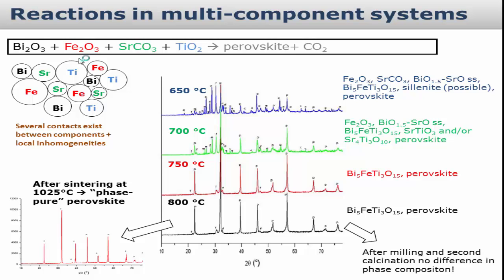This is an X-ray pattern of the mixture of these 4 at different temperatures. You can see that there are several phases that are formed. These patterns are very complex, so we were not sure about all phases, but we know that it's a multi-phase mixture. Some phases appear at higher temperature than others. For example, here we have this bismuth-strontium solid solution with a relatively low melting temperature, and that's dangerous, as I will show later.